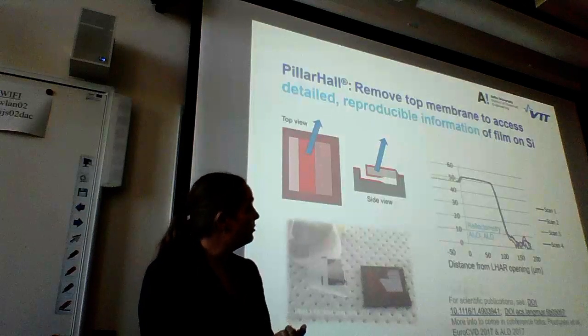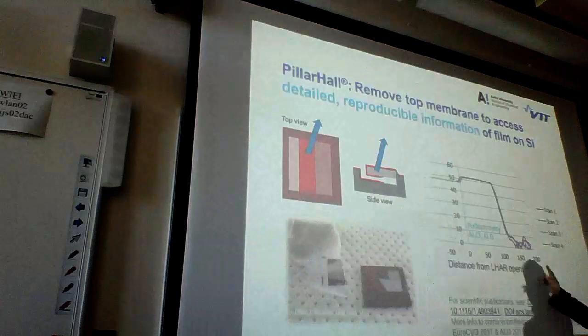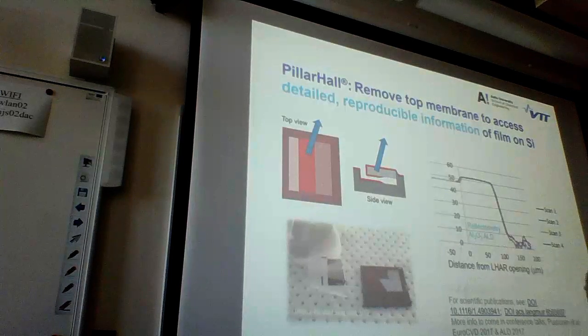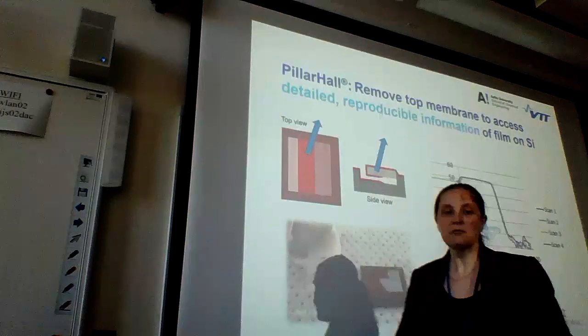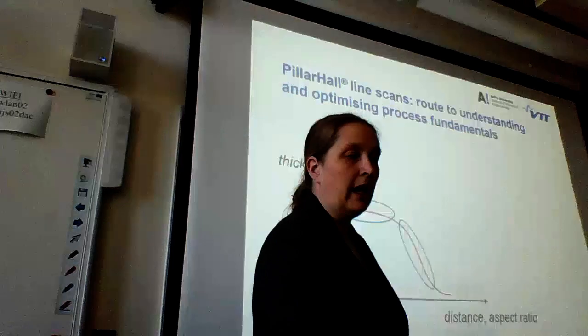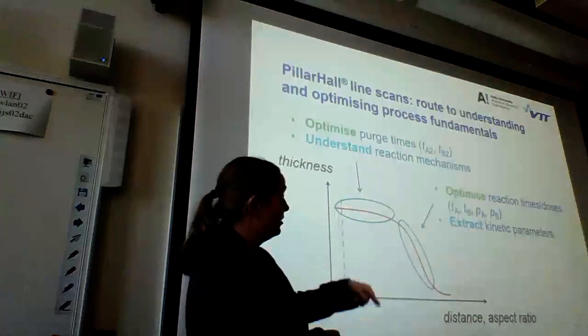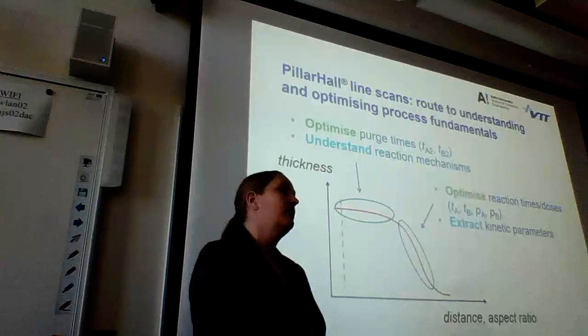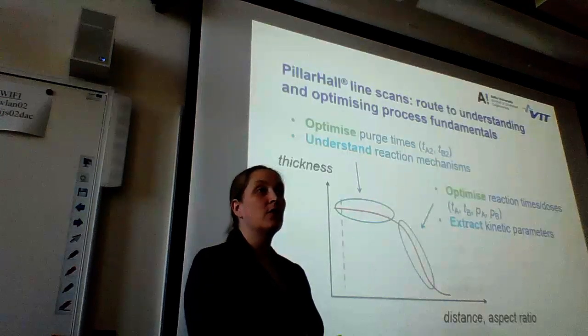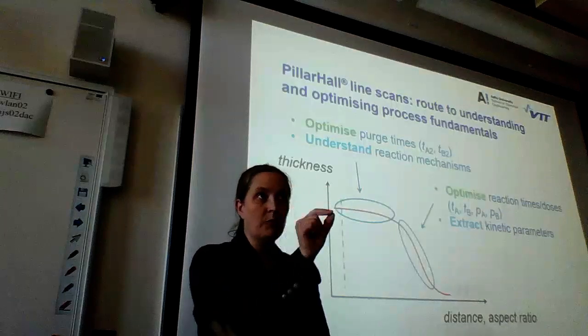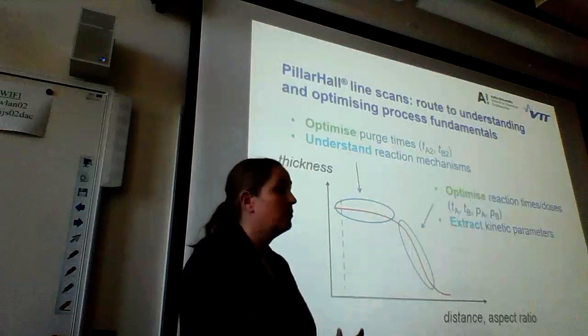This one you can measure by many means, I think. We have done it by reflectometry, and here are just repeated line scans. This is for the basic TMA process. You see, you always get the same result, so the repeatability is very good. And here we see basically the shape that we would expect for a good ALD process, that you have just a constant plateau, after which you have a fast decline of the thickness. And the interesting thing is here, the previous figure had like 200 points. There has never been access to such information earlier, because when you have these vertical structures, you measure point by point. It's very, very tedious to do something like wafer mapping.